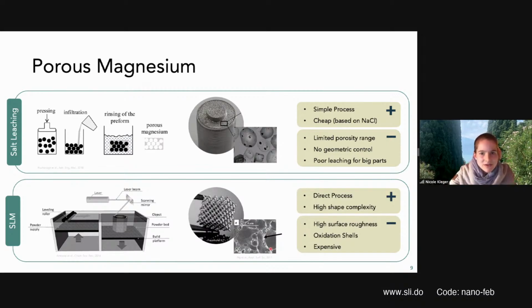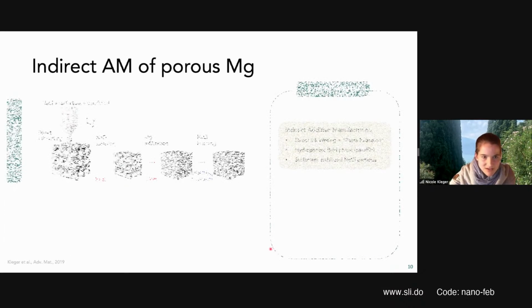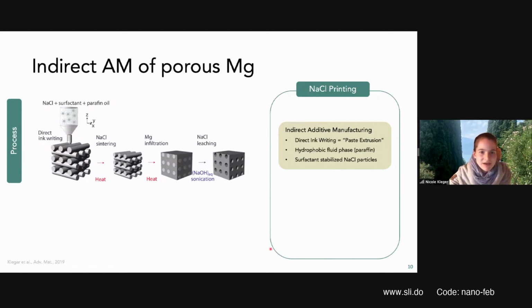So what we are doing in the lab now is combining the best of these two approaches. So let me quickly guide you through the process we develop. We 3D print a salt-loaded ink, so by direct ink writing, which is an extrusion process where we push out an ink through a nozzle and deposit it layer by layer. Then this 3D printed part is sintered to have pure salt scaffold. It is then infiltrated with magnesium, and then the salt can be washed out to get the scaffold.